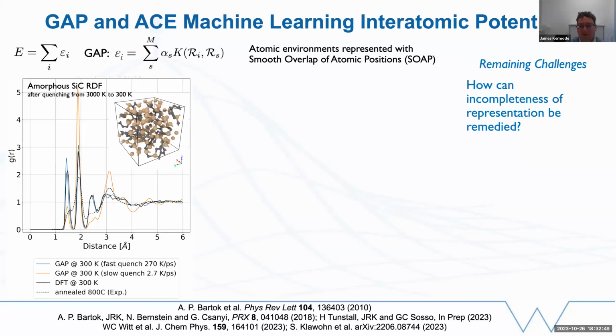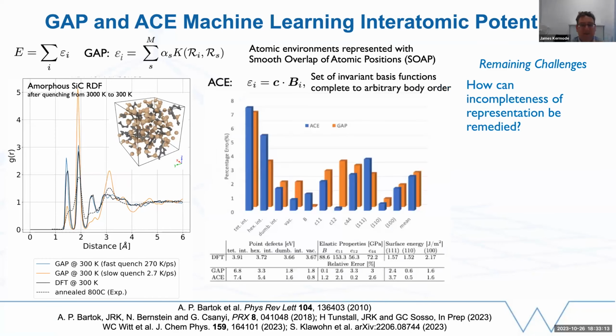One of the challenges of these kinds of methods is accurately describing the environment, and a limitation of SOAP, the smooth overlap of atomic positions, is that it doesn't fully do that. It's only complete up to three-body interactions, and you may want to go to higher body orders in order to more accurately describe the environment. And one successful way of doing that is with the atomic cluster expansion approach, ACE, introduced by Ralf Drautz a few years ago, which actually can be used in quite a simple linear setting.